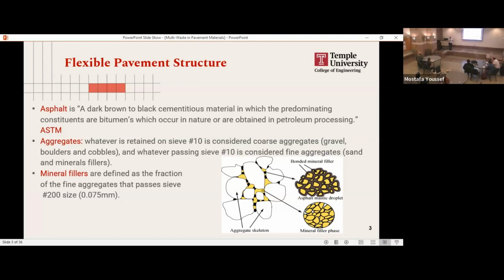And the binder itself is not just the asphalt also. Like we were talking earlier, it is the mastic. It's the blend of fines and asphalt. The weakest link in this structure is the binder. So we typically have failures starting with either overcompaction during construction, crushing the aggregate, but that can be mitigated through good quality control during construction, or failure within the mastic phase, which takes place either if you're using very soft materials, so it acts like a lubricant between these particles, letting them slide against each other and deform, like in the form of rutting, for example, or if the asphalt itself is aged so that it would crack.